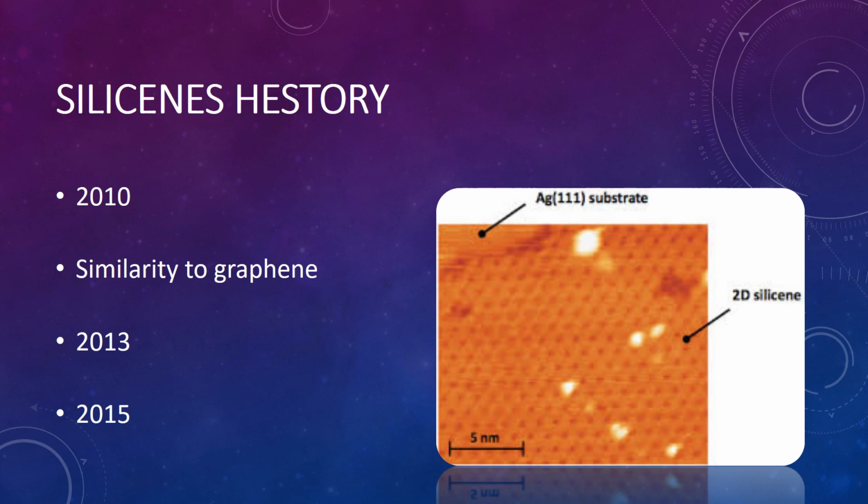However, such a model has been invalidated for the Si/Ag(111). The Ag surface displays a missing row reconstruction upon Si adsorption, and the honeycomb structure observed was artifacts. This was followed in 2013 by the discovery of dumbbell reconstruction in silicene, which explains the formation mechanism of layered silicene and silicene on Ag.